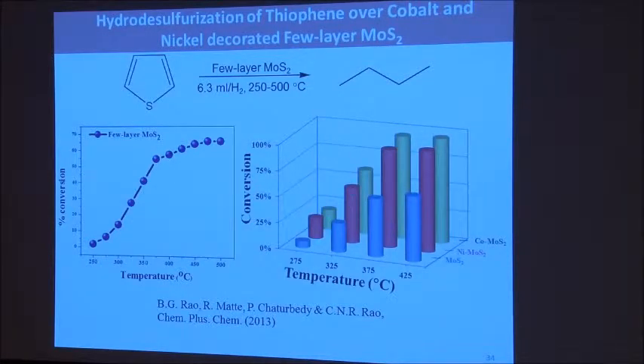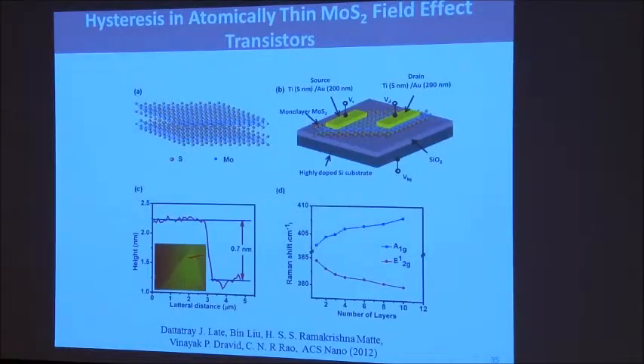Even starting at a very low temperature, you almost get 100% desulfurization by around 400 degrees. So these are some of the interesting chemistry associated with this material.